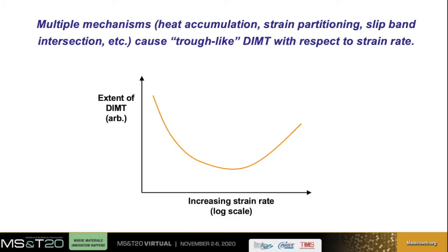Based on experimental data from this study and a review of previous research, I postulate that the strengthening contribution of TRIP is controlled by the competing effects of, first, a decreased chemical driving force for deformation-induced martensite transformation that is caused by deformation-induced heat accumulation at higher rates, second, an increasing number of martensite nucleation sites, and third, an increasing mechanical driving force due to strain partitioning from ferrite and martensite at low rates to austenite at high rates.